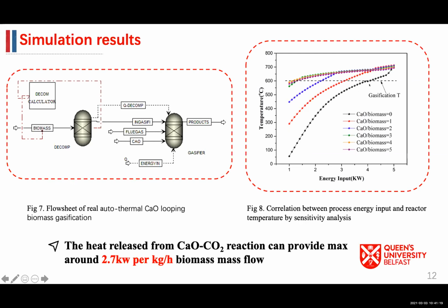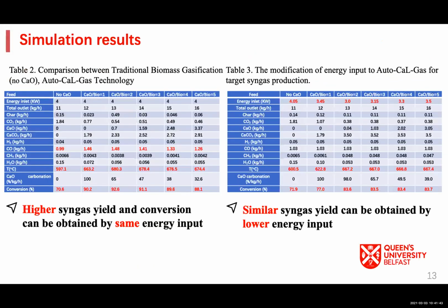In order to achieve 600 degree gasification temperature, the required energy input is around 6 kilowatts. But with the increase of calcium oxide to biomass ratio, the required energy becomes less and less. And our process can provide maximum around 2.7 kilowatt per kg per hour biomass mass flow. So from the simulation results, as shown in these two tables, higher syngas yield and conversion can be obtained by same energy input, and similar syngas yield can be obtained by lower energy input, which is consistent with our innovation.